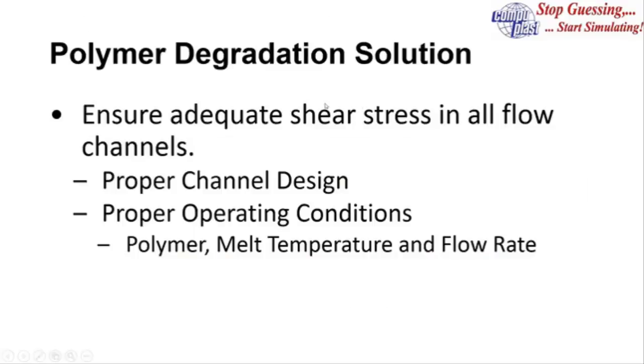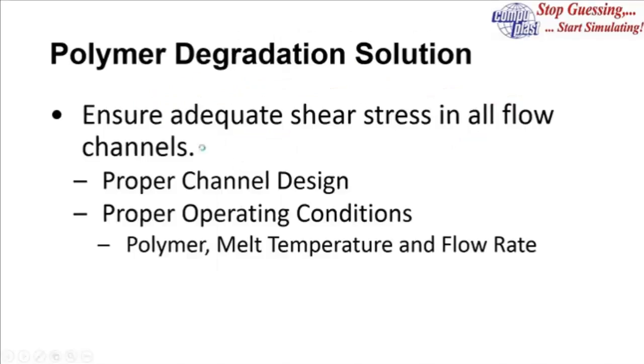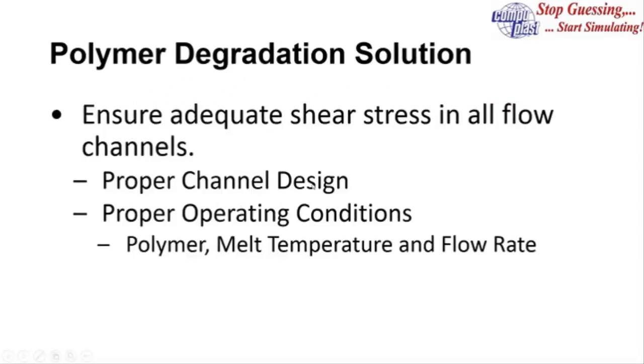So the solution to polymer degradation is to ensure adequate shear stress in all flow channels. And ensure you have a proper channel design and proper operating conditions, because the most highly polished and optimized channel will still degrade if you're running the polymer that wasn't designed for it, or you're running a very high melt temperature from your extruder, which reduces the viscosity and reduces the shear stress at the wall from what it was designed for, or if you're running at a much lower flow rate than the die was designed for. So we need proper channel design and proper operating conditions in order to avoid degradation.